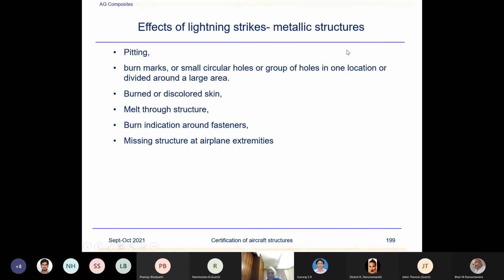The effect of lightning strikes on metallic structure is normally pitting, burn marks, or small circular holes or a group of holes in one location, or divided around a large area, burned or discolored skins, melt-through of structure, burn indication around fasteners, and missing structure at airplane extremities. Normally metallic structures don't suffer as much damage as the composites, just small damages.